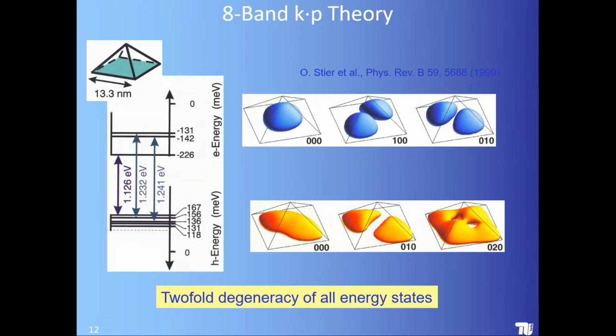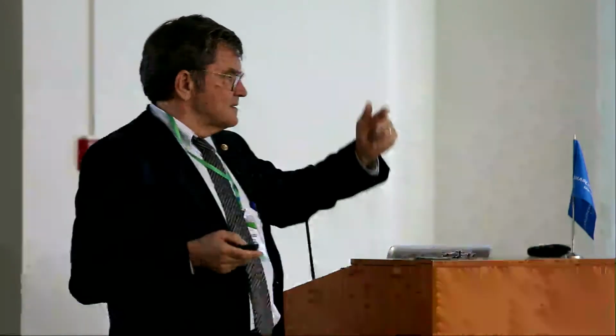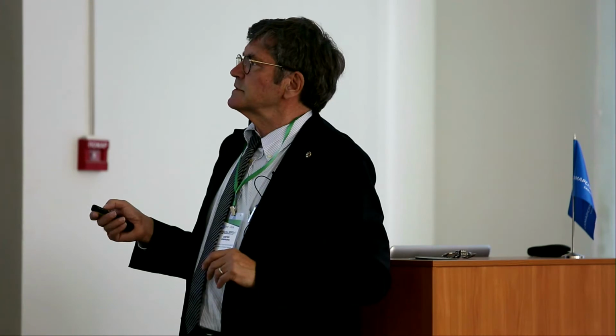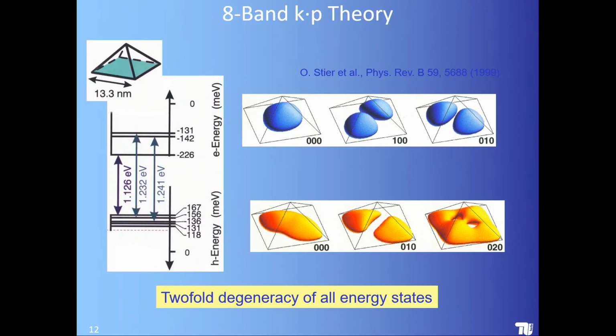And here are some wave functions which we calculated based on 8-band k·p theory. You see that you have energy level structures. What is most important for electron and hole levels is that all these levels show a twofold degeneracy of the energy states. That means the energy level structure of a quantum dot is simpler than a hydrogen atom. In a hydrogen atom, you have s, p, d states, etc. Here, you have only twofold degeneracy. The ground state wave function for the electron still looks a little similar to an s-state of hydrogen. The px and py states look a little similar, but are split by a certain value. The whole wave functions show no similarity anymore with any atomic wave functions.